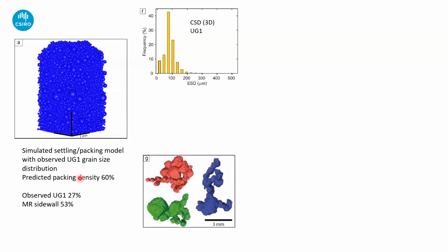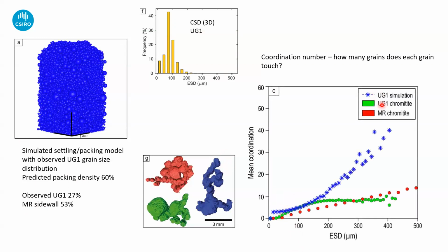Now, the other thing we looked at, and this is the more innovative thing we did in this study, is to look at a thing called the coordination number. The coordination number is the number of chromite crystals that each chromite crystal touches. This is basically a way of measuring the openness of a framework. How many grains does each grain touch? So this is the blue simulation here. That's this model. And what that shows is that you expect a more or less linear increase of the coordination number with grain size. That's kind of intuitive. The bigger the grain, the more other grains you would expect it to touch, right?